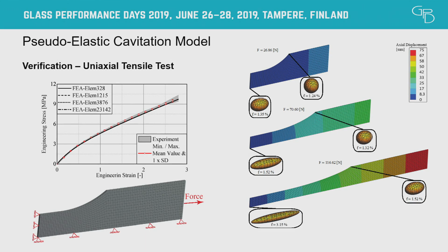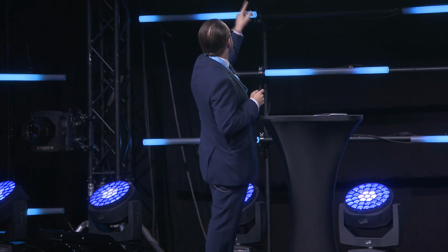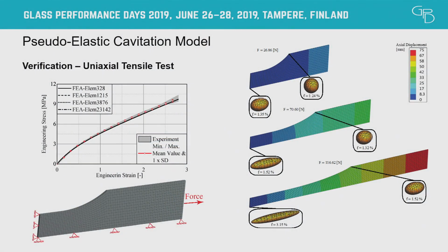Since this is a material model implemented in ANSYS, we have to check and validate the model with experimental results. And this is what you can see here. In gray, you can see the stress-strain behavior of our TSSA in the dog bone test. The experimental curves are always displayed in gray, and in black, you can see the numerical simulation of it.